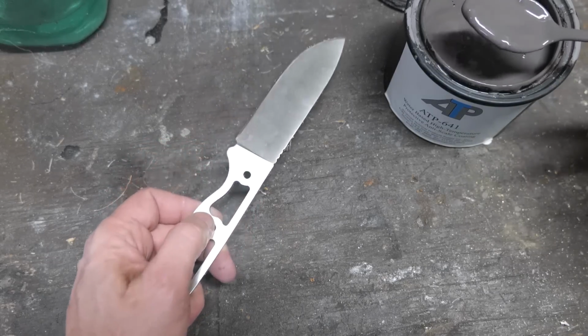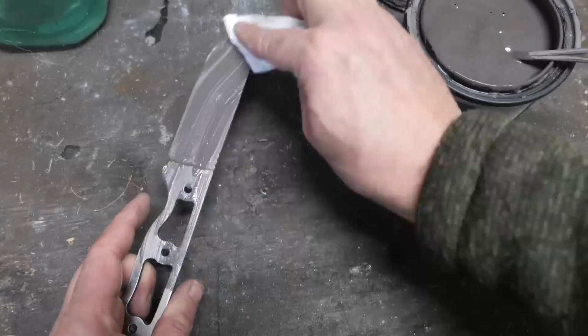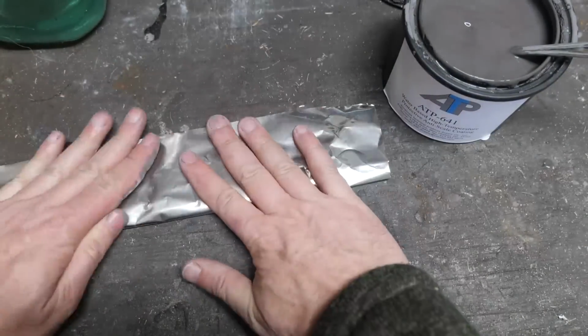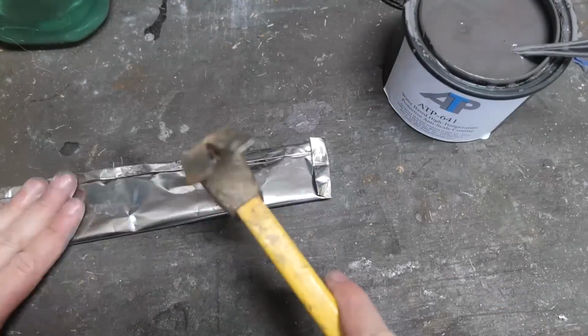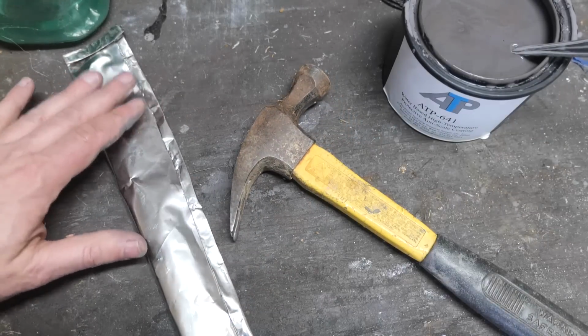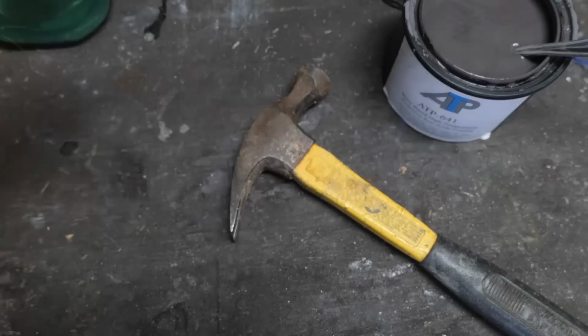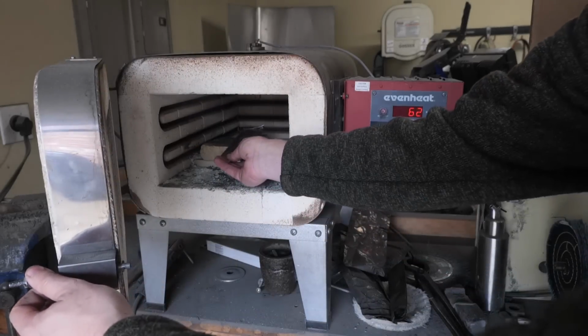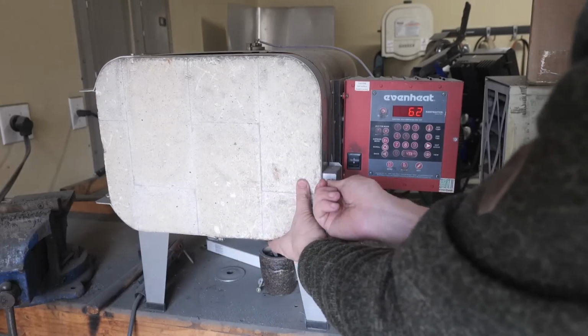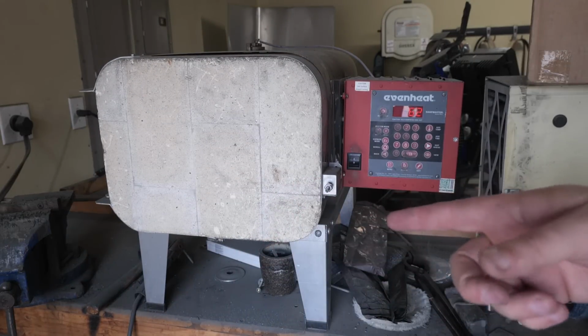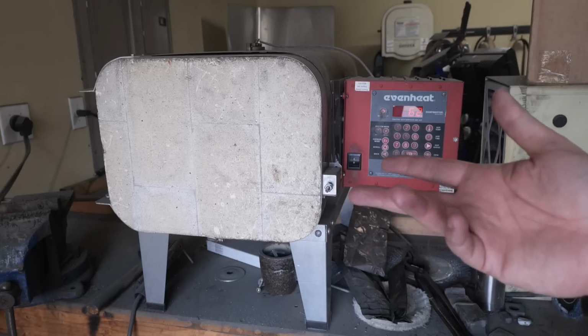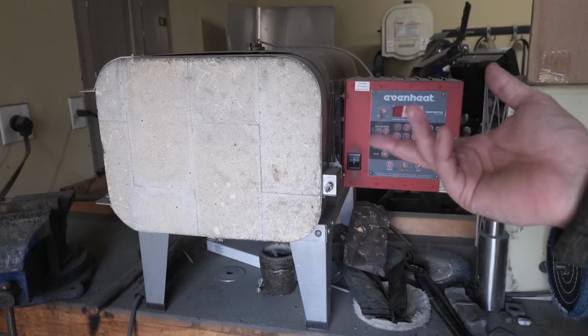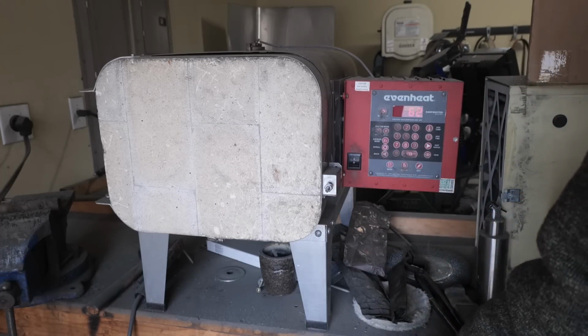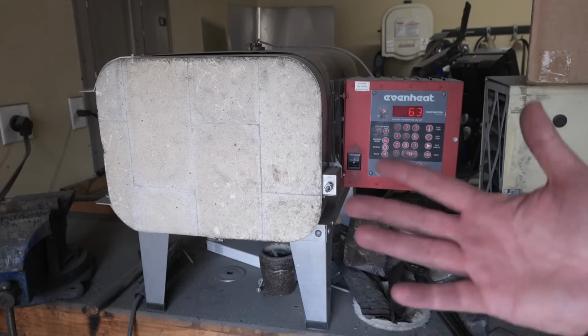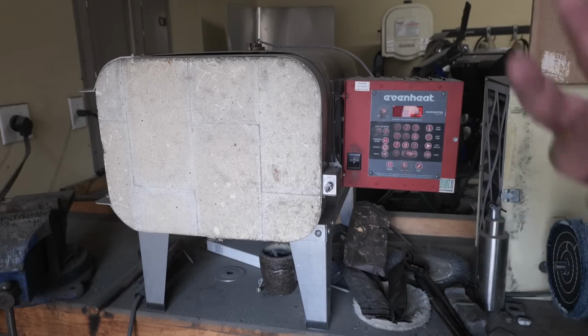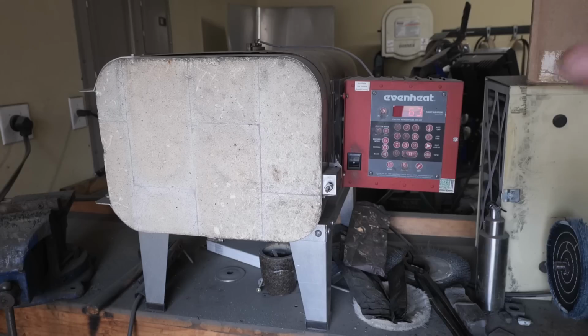Heat treating D2 takes high temperatures for prolonged soaks, so I'm going to put some anti-scaling compound on here to help prevent scale, oxidation, and decarburization the best we can. It's on a slow ramp to 1100 degrees where it equalizes, then a faster heat to 1450 for more equalization, then 1825 equalizes again. Then we're going to sort of plate quench it, the handle at least, and let the rest of it air cool. That should harden it up, then temper at 300 degrees so we keep it nice and hard. Hopefully if it's D2, that'll bring it to about 62, 63.